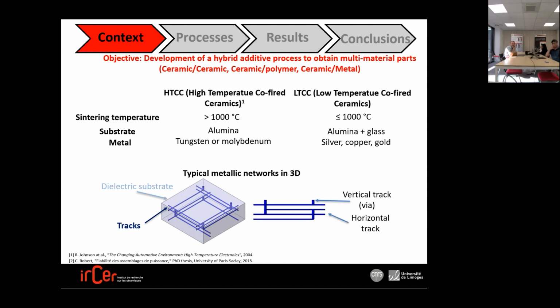As it has been presented before, we would like to develop a hybrid additive process to obtain multi-material parts, for example, ceramic or ceramic polymer or ceramic metal. In the next slides of my presentation, we will only deal with ceramic metal parts. In this way, there are two types of parts, the HTCC, high temperature cofired ceramics, and the low temperature cofired ceramics. For the first one, the sintering temperature is higher than 1000 degrees Celsius. The substrate is generally alumina and the metal can be tungsten or molybdenum. In the other way, LTCC parts have a sintering temperature lower than 1000 degrees Celsius, and the substrate must be alumina and glass, and then the metal can be silver, copper, or gold. What we are going to present you in the next slides is only with HTCC material.